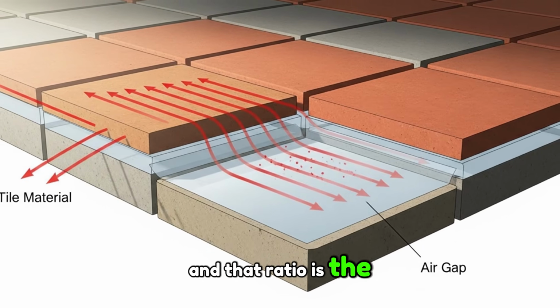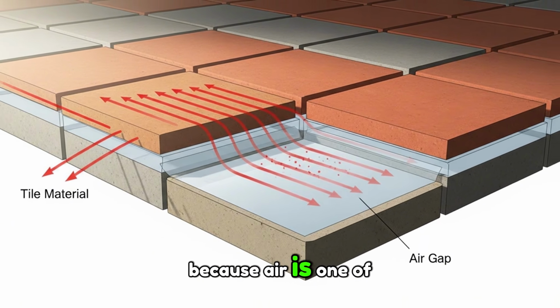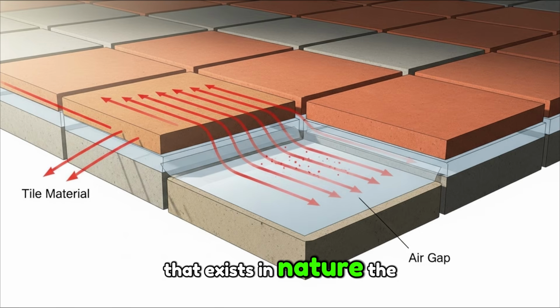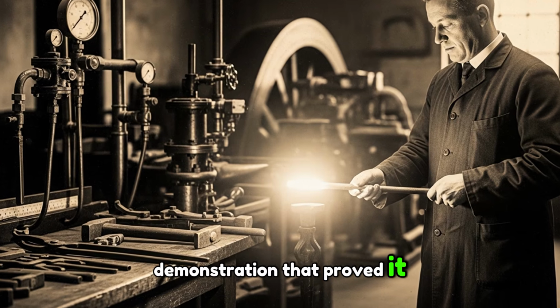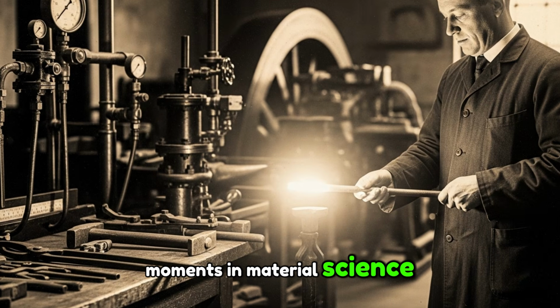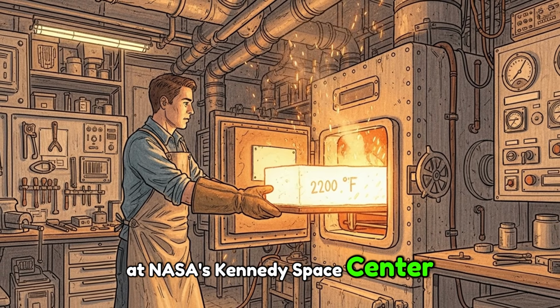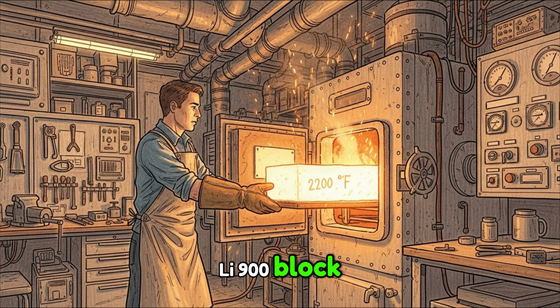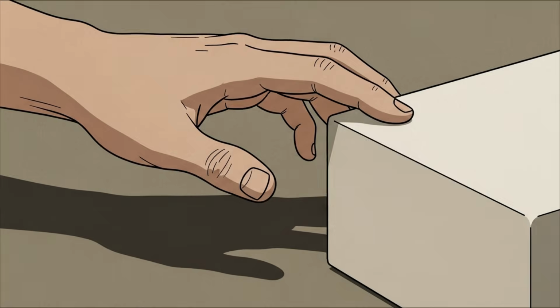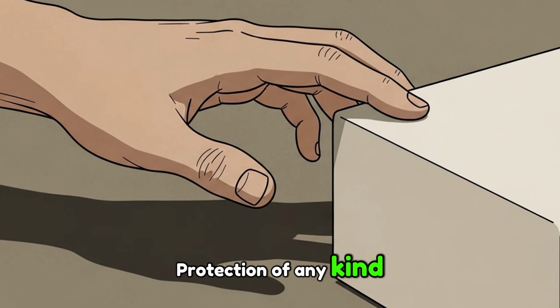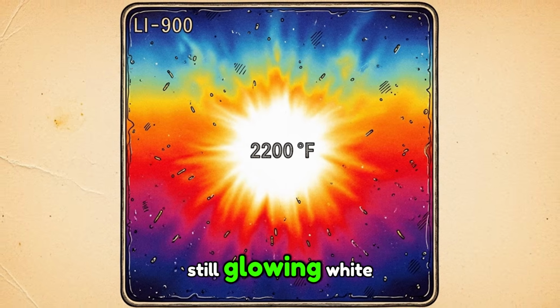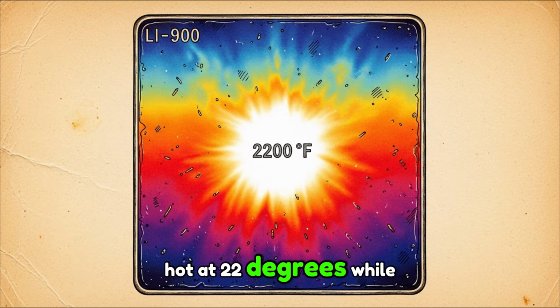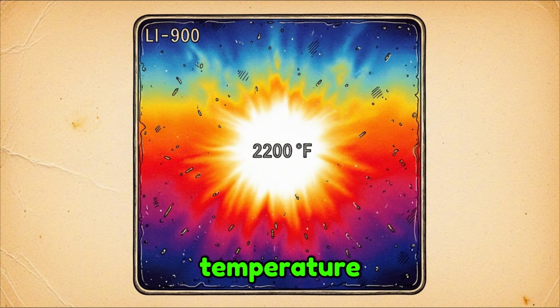And that ratio is the entire reason the tile works, because air is one of the worst heat conductors that exists in nature. The demonstration that proved it became one of the most famous moments in material science. At NASA's Kennedy Space Center, engineers would pull a glowing LI-900 block straight out of a 2200 degrees F oven, set it on a rack for just a few seconds, and then reach in and pick it up by the edges with their bare hands. No gloves and no thermal protection of any kind. The center of the tile still glowing white-hot at 2200 degrees, while the corners have already dropped to room temperature.